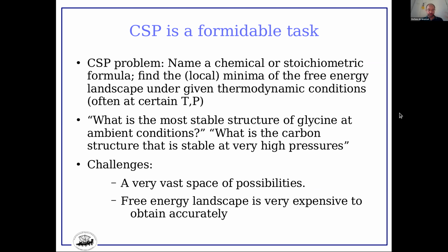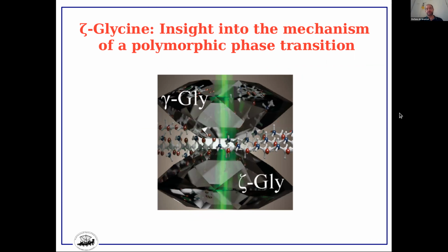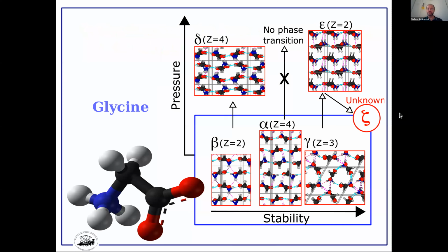And so for instance, to name one system that we looked at recently, well, recently means 5 years ago or so, is glycine. Glycine is the simplest amino acid, is a 10 atom molecule, and has a number of phases. So the glycine has 3 phases that are known at room temperature: alpha, beta, gamma. Alpha is the easiest to crystallize, to find. The most stable actually is the gamma phase, which is somehow difficult to obtain, but if you do calorimetric measurement, you find out that the gamma phase is indeed the most stable.